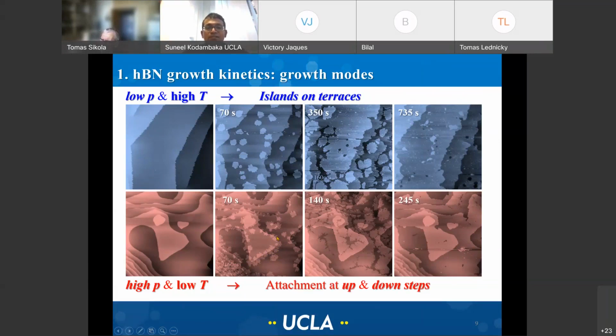But this is the onset of the so-called carpet-like growth that happens in these 2D layered materials. The other unusual aspect is that at lower temperatures, we observe attachment and growth at the step edges, and at higher temperatures, we observe island formation. This is opposite to what is conventionally observed in traditional thin film nucleation and growth kinetics.